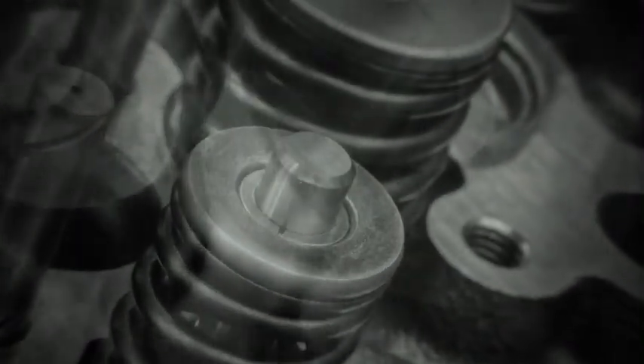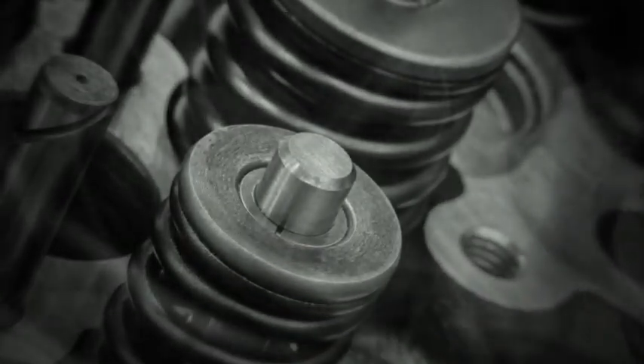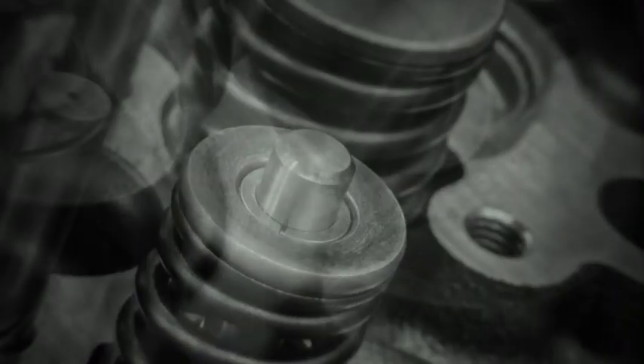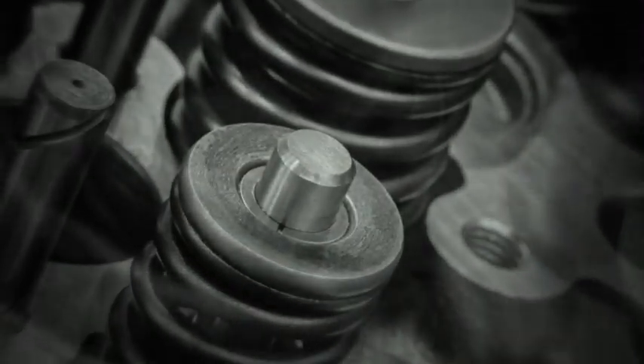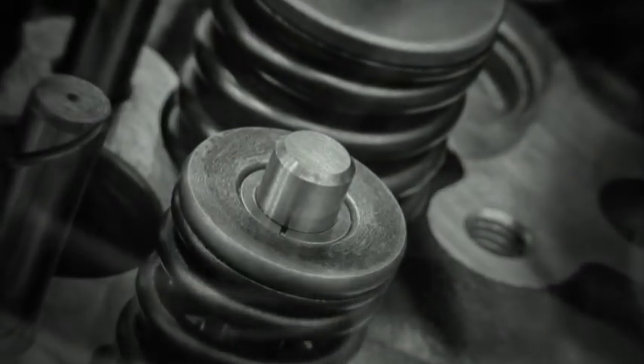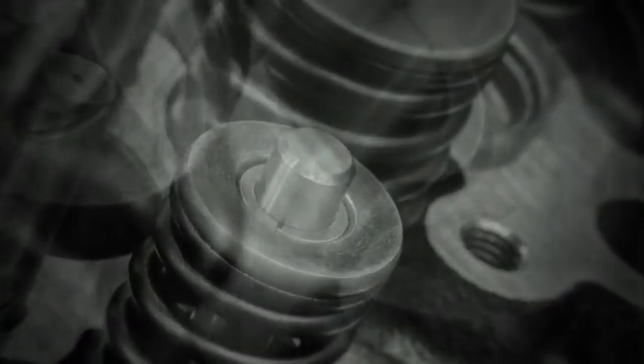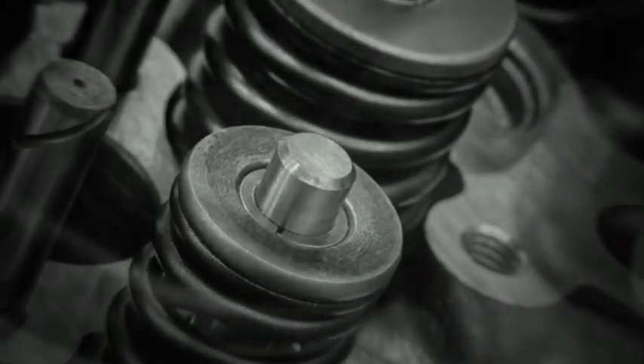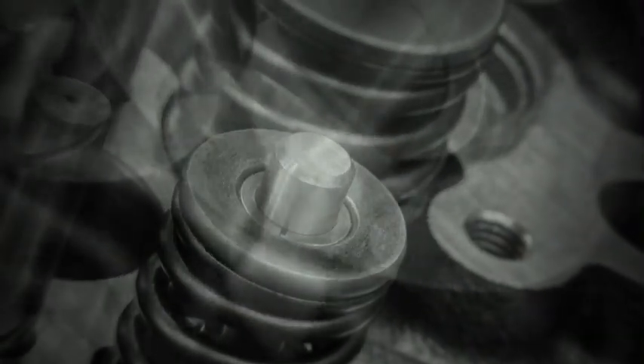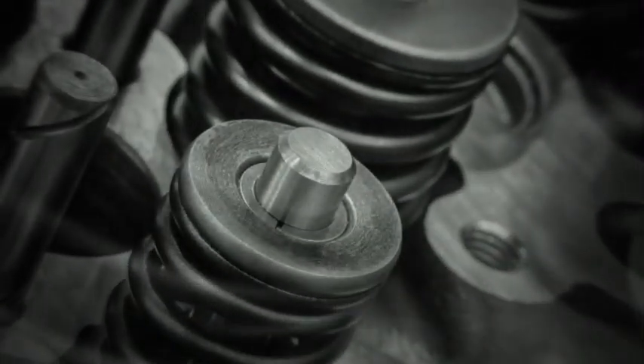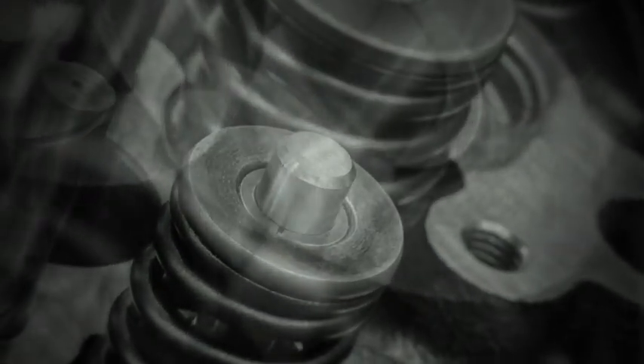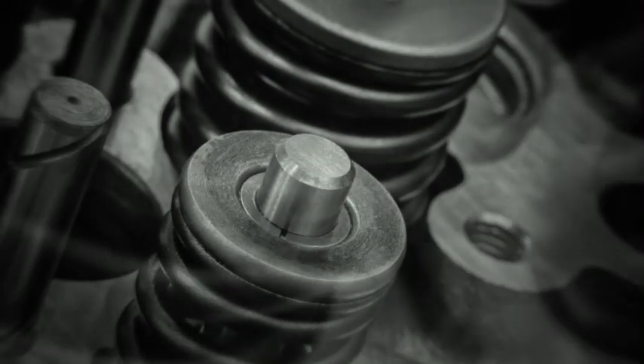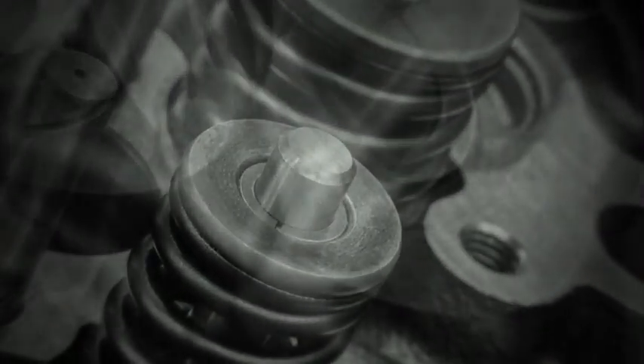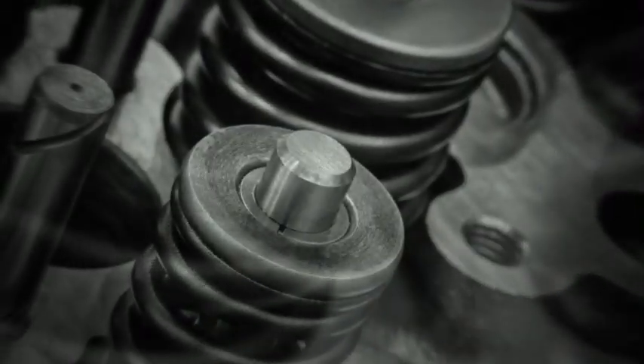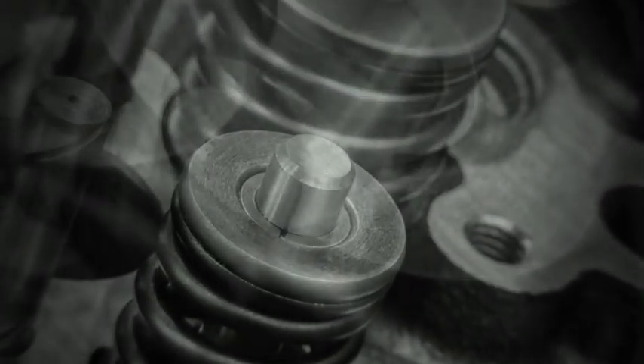Fretting occurs where a spring rubs through small, repeated movement against a seat, guide, or neighboring coil. The surface becomes polished, oxidized, and damaged. The wear mark can become a crack origin. Coil bind creates high contact and impact when adjacent coils close completely. A spring compressed beyond the intended travel may not have space for wire tolerances, dynamic overshoot, or deflection of the surrounding structure. Buckling changes the load from controlled axial torsion into bending and rubbing.